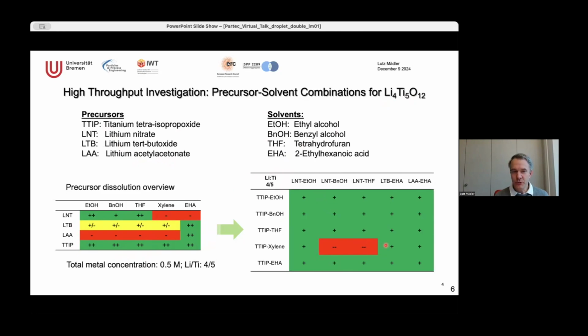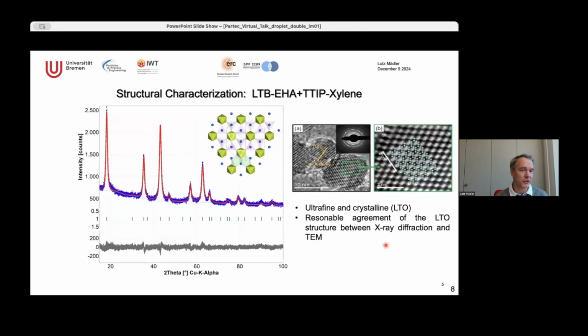And once you have that solution, you just need that reactor, burn everything, collect the particles, and look at what you get. And this is what you get. This is, of course, our best case here. That's why I'm showing it. And this is really lithium titanate. And it's very phase pure. I'll show that to you in a second. You can see that here on this XRD pattern. It matches the lithium titanate perfectly.